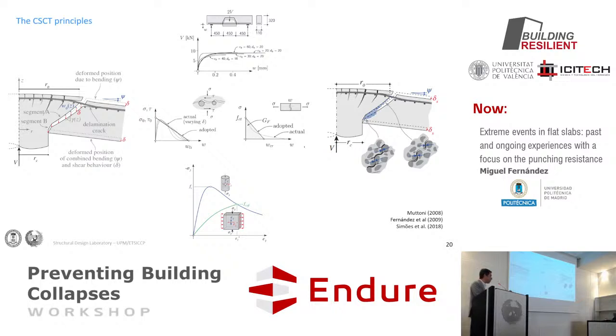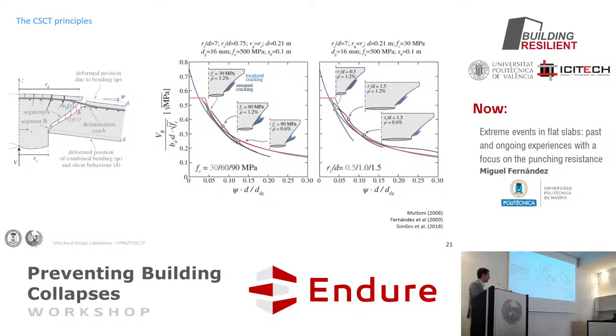By the way, you can do this and solve this numerically. These are, for instance, numerical solutions for different cases, and you can see that psi is associated to rotations. The larger the rotations, the more the cracks open, you transfer less through aggregate interlock on top, and everything concentrates on the bottom. However, when you have small levels of rotation, small levels of deformation, cracks are not that open, and then you can mobilize this transfer of shear stresses through larger regions. And this is consistent with what we were seeing before, that the lower the deformation, the higher the resistance you could have.